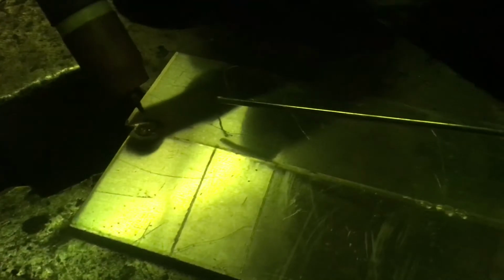Here's another shot of this. So you can see I'm starting, just letting it sit for a second, and I'm dabbing, pulling the filler rod back quickly. This is a good example. This weld has some contaminants coming through. Closer to the end, you'll see the arc get unstable, and it actually almost looks like it pops. And that's either the tip of the electrode touching into the molten metal, and it's going to create some black haze on there. So be careful of that.